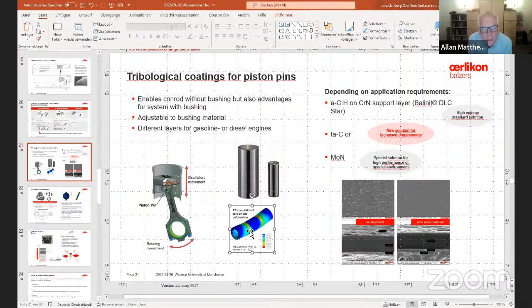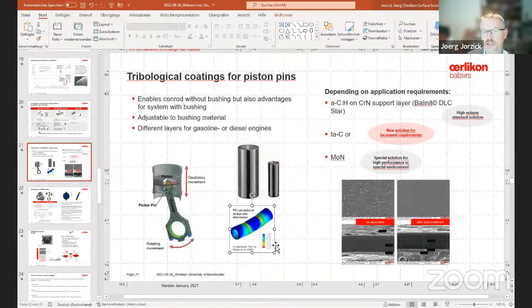And it's similar also to the differential shaft, and that is also the reason why these, let's say, electroless nickel coatings are not working, because the deformation is just becoming too large. Yeah. So this is really something where the PVD coatings show an excellent behavior, and also because you have not only this very hard surface, but you also have this ductile coating underneath that helps us to survive this kind of harsh applications. Because I mean, basically you have this very hard and of course also brittle DLC like coating on the surface, and then you do these wild things with that.